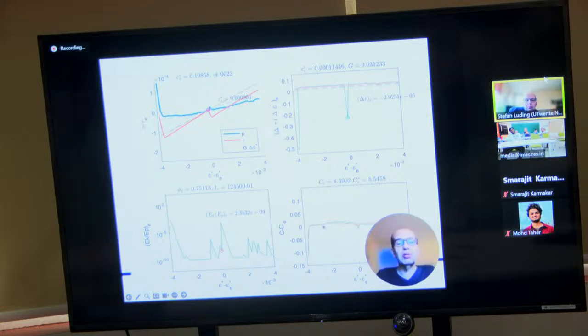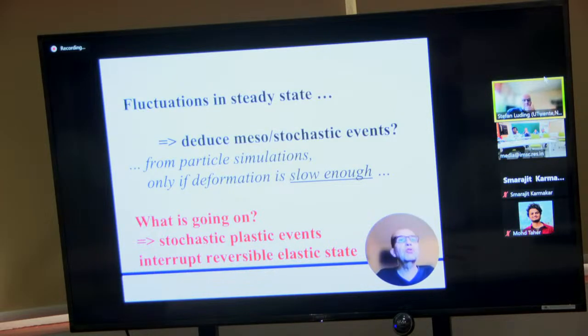Here not much is happening, but there are much more violent events where the microstructure, the contact network, is changing the coordination number a lot. So in summary, what we learned from our particle simulations, and I didn't make that clear yet, is that only if you really go very, very slow can we identify these isolated events. Isolated events are plastic, irreversible, and they interrupt the reversible elastic base state.